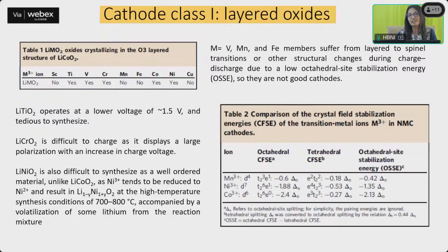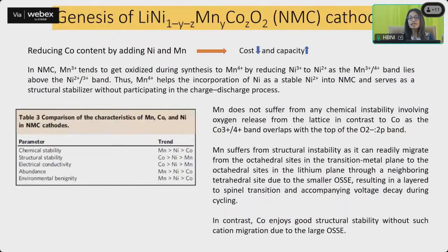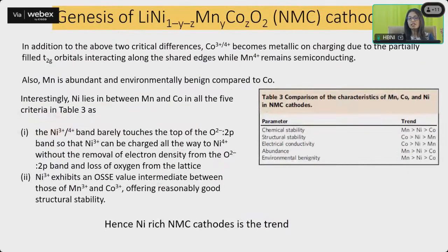It is basically degrading. Whenever you are cycling this material, when lithium is moving out and lithium is moving in, it has to hold that structure. If in between, when all these different processes are taking place, your oxygen has already moved out of the structure, then you end up with a structure which is already degraded. So even if the lithium comes back, it cannot sit in its original position. Because the structure is degraded, it is not going to hold on to the specific capacity, and with continuous cycling your specific capacity is going to go down. So you cannot use that battery for a long cycling process. That is the problem.